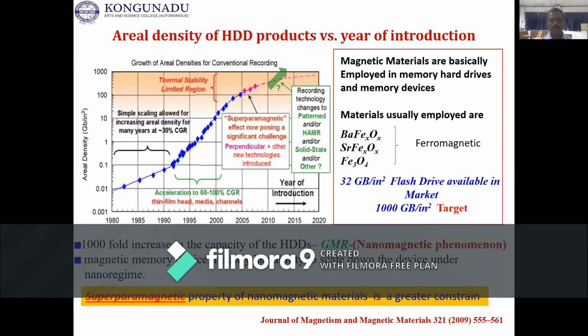But the superparamagnetic property of the nanomagnetic material is a greater constraint, and it doesn't allow the reduction in size because of its thermal instability. Around 2020, the diagram shows that at 100 GB per inch square, thermal stability of these magnetic layers is a problem. In memory devices, barium ferrite, strontium ferrite, and iron oxide are the usual magnetic materials used. Earlier, in 2010, 100 GB per inch square was the target of companies to achieve the maximum storage.